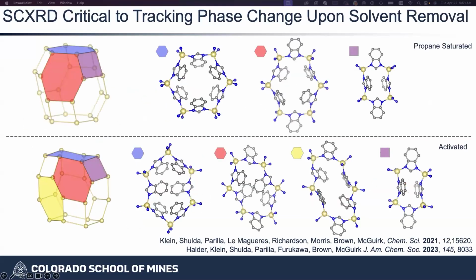And so this was the first time we started working with Pierre. And we actually got this beautiful structure from single crystal by accident. So I don't know if you remember what happened here, but we sent him a sample where we had made this with DMF in the pores, and we had slowly exchanged the DMF that was in the pores of the framework for chloroform. And we knew that there was still some chloroform there, but we really wanted a structure where there was nothing in there. Pierre took the crystal, put it in the oil, and then mounted it and got a crystal where it was completely solvent-free. Turned out the chloroform had diffused out of the crystal into the oil, and we got a completely solvent-free crystal that really changed a lot of the trajectory of our research. So that was a beautiful accident. And so what we see is that when we make this system, we have this open pore phase.